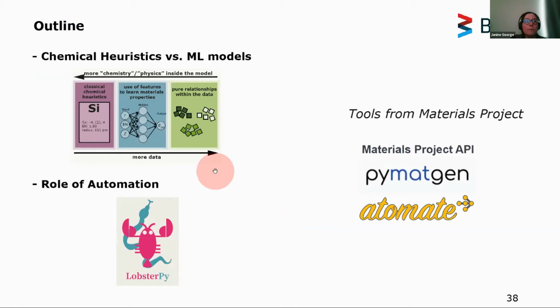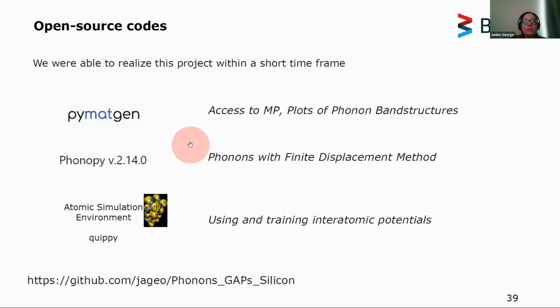Now I'm switching already to this part on automation, but it's still connected to these phonon computations. I wanted just to highlight that we were actually able to realize the large project that I was talking about in a very short time frame, because we could rely on open source codes. So we had Pymatgen to access the Materials Project. We were able to plot the phonon band structures, compute the densities of states, and so on with the help of Pymatgen. We used Phonopy to compute phonons with the finite displacement method. And for the interatomic potentials, we were able to use a combination of GAP and the Atomic Simulation Environment.